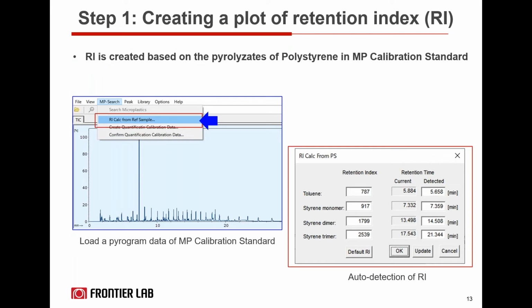So this is step 1, and again, I'll show that in a few seconds via the live demo, but this is to give you an idea of how the software will do that for you. In step 1, you load your sample, and then you do the RI calculation, which is based on the pyrolysate of polystyrene. The system automatically does an auto detection of the RI, but you can also change the values, especially the retention time, in case you want a slightly different retention index.